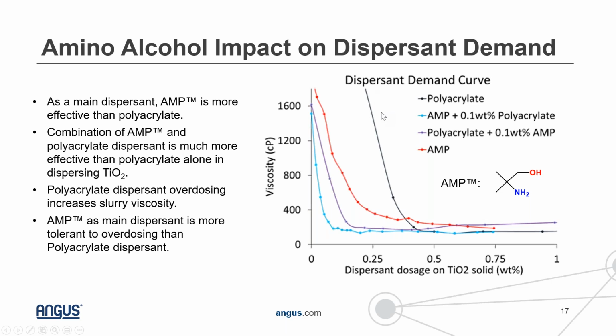And so what we see for a typical polyacrylate dispersant, that's the curve in black, is that as we continue to add this dispersant to that grind, we see the viscosity decrease, and we see a minimum viscosity, which usually indicates the best quality grind you can achieve, at around 0.5% of that dispersant on pigment solids. If you compare that to the case of AMP, which is shown in the red curve, what's obvious is that just a little bit of AMP can have a pretty dramatic effect on the viscosity. It doesn't take very much AMP at all to really start to drop the viscosity of that grind.